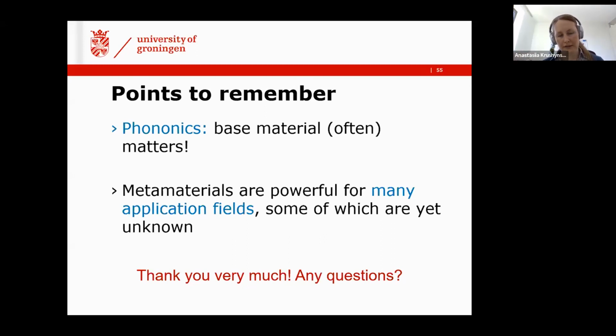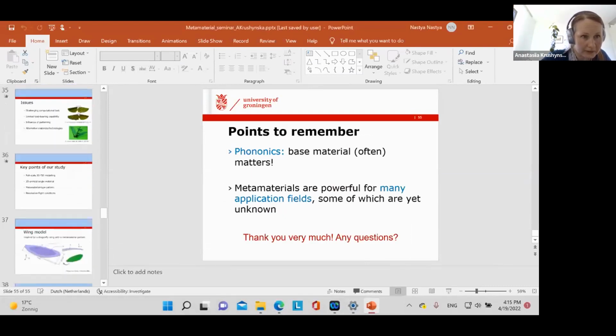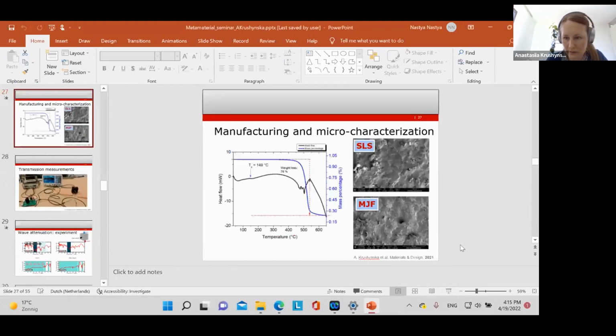Yeah, it's definitely important because when you print a structure which is longer than 10 centimeters, the variation in properties of the material is very different, starting from the material density, because the initial part of the structure, which is located, so let me now come back to that schematic of the printing technique. So this will be more understandable, I guess. So it's here.